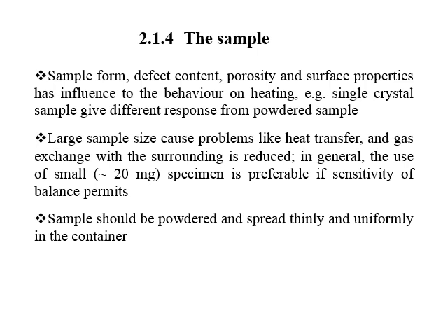Large sample sizes cause problems like heat transfer and gas exchange with the surrounding area. If you have a very large sample size, kind of like a single crystal, you have a large thermal mass that's going to heat from the outside in and slow the reaction. Correspondingly, you may have reaction products that also slow down the reactions by increasing localized partial pressures and changing the reaction rate. So in general, a small sample size is preferred.